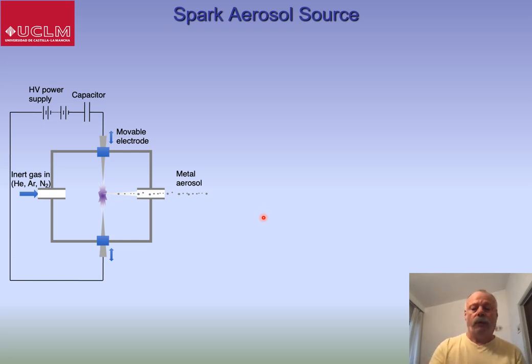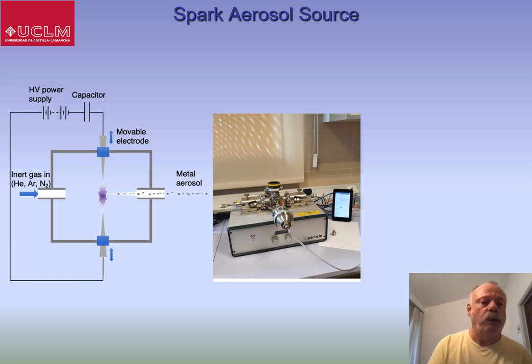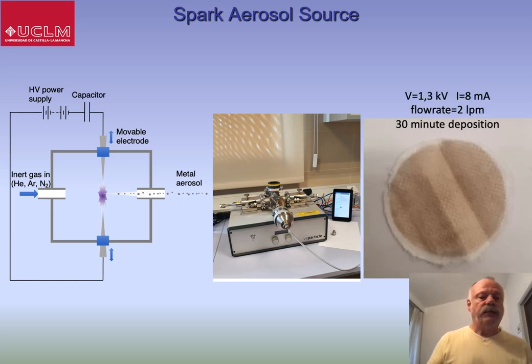Now, the device itself is quite small, it's an under-tabletop device, and we coated the cloth by sealing the material on the exhaust of the source so that the aerosol was blown through the material. And as I'll show, this was a good way of coating the nanoparticles through the entire volume of the material.